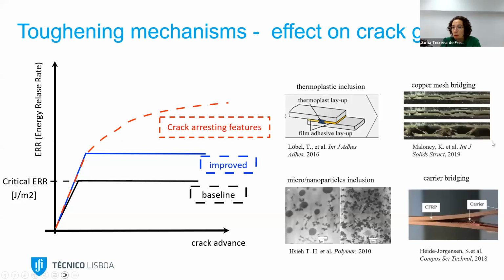So for this one, there are also many examples in literature, but I just keep here two, in which we create bridging mechanisms between the two substrates, either created by a mesh which is incorporated in the adhesive, either a polymer mesh or a copper mesh. And by creating these bridges between the two substrates behind the crack tip, we can arrest the crack even further.